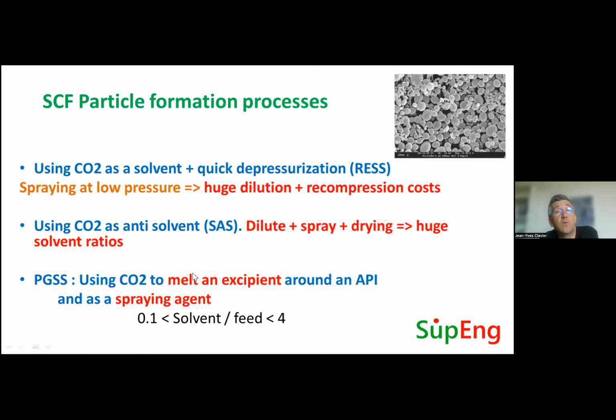Going continuous is also a way we try to develop in the crystallization and particle formation process. I don't want to detail all of them. You can use CO2 in different ways, either as a solvent, and then you depressurize to form some powders. You can use CO2 as an anti-solvent to dilute a liquid solution to crystallize a solid. These two processes, because of low solubility, or because you have to use it as an anti-solvent, then to spray, then to dry the powder, usually bring to very high dilution. And this is only used for pharmaceutical because this is very costly.